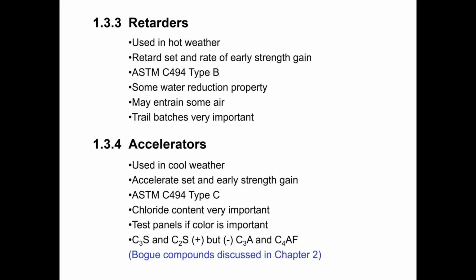Okay, next is retarders. So generally a retarder is going to be used in warmer weather to help slow down the initial set and the initial strength gain of the concrete. So we're going to retard that set and early strength gain so that we've got more time to get the concrete placed, consolidated, and finished properly. Retarders are covered by ASTM C494 Type B. Just like some water reducers have retarding effects, some retarders have water reducing effects. Generally, that's going to be to the plant's advantage if they're using a retarder that has some water reducing effects.